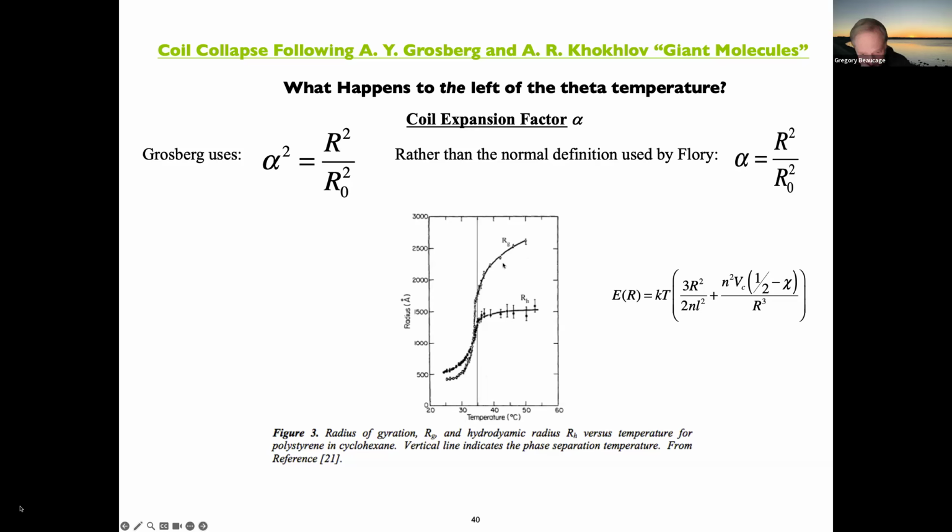So all these derivative terms have a discrete value in what's called a second order transition, and they go to infinity if it's a first order transition, like a melting point. When you melt ice, there's a step change in the volume. The specific volume goes up. So basically, there's a step change in the volume, a step change in the enthalpy, a step change in the entropy, a step change in the free energy. That's a first order transition in melting.